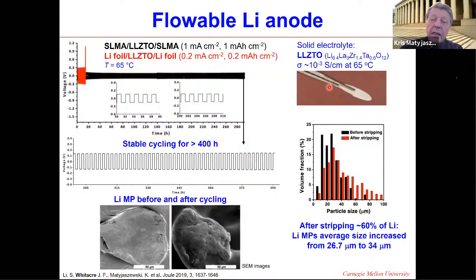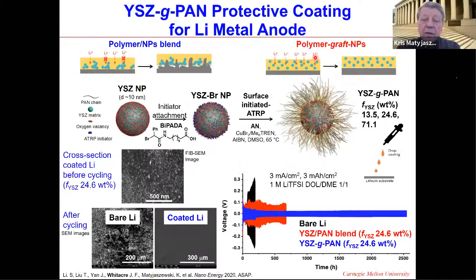Another approach, on the last slide, really shows that you can have these solid electrolytes with very good properties. This is yttria-stabilized zirconia nanoparticles. They can be either blended with a polymer or grafted with a polymer. And there is a dramatic difference if you start grafting, because you have a very uniform distribution and the dendrites are strongly suppressed. You could see here on this graph, using 3 milliampere per square centimeter, this is what happens with a bare lithium.